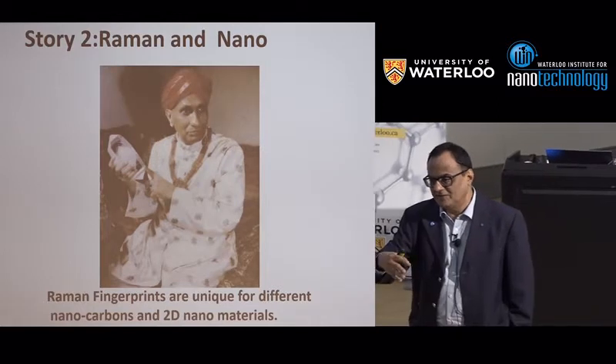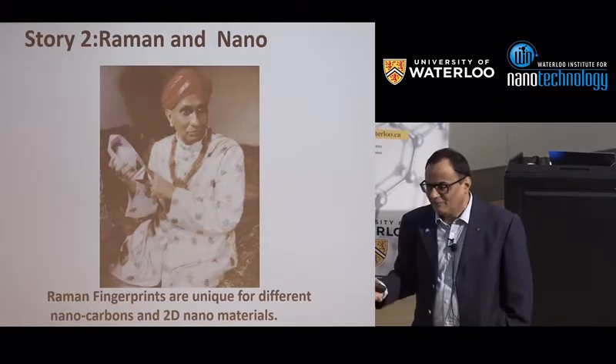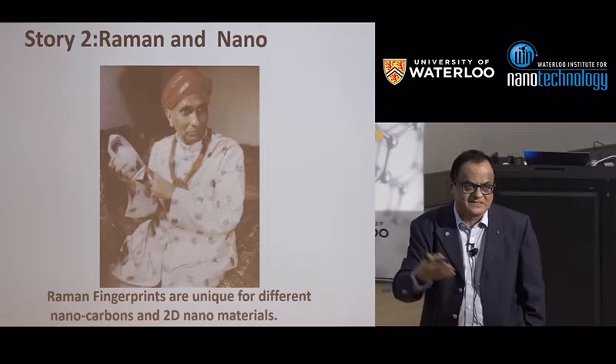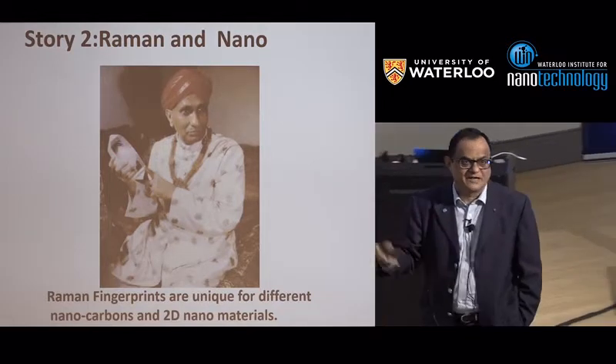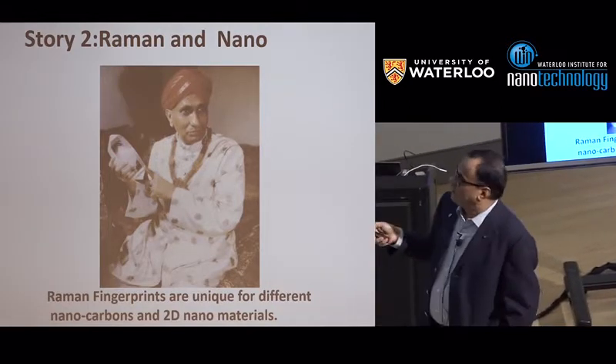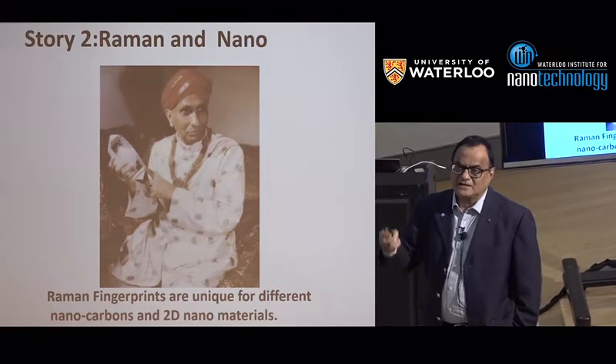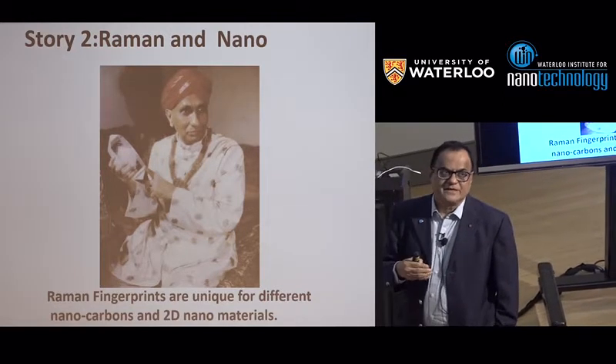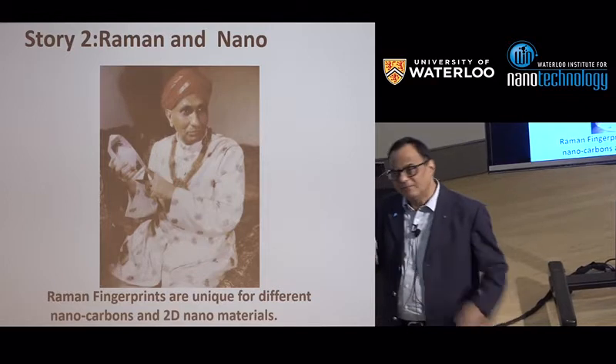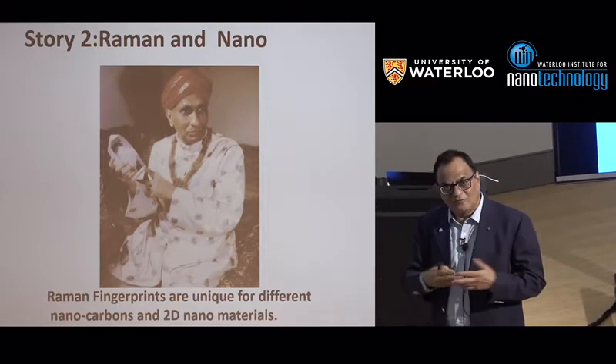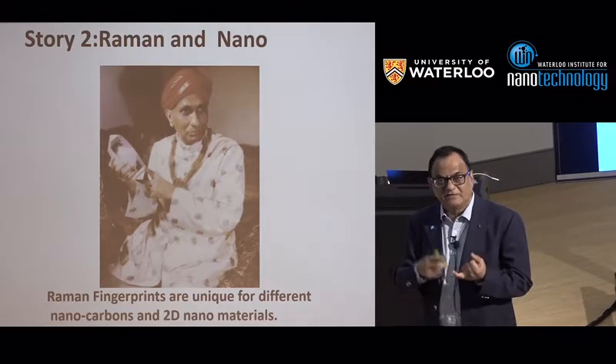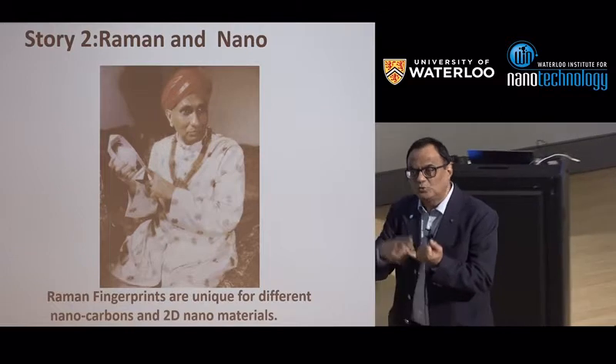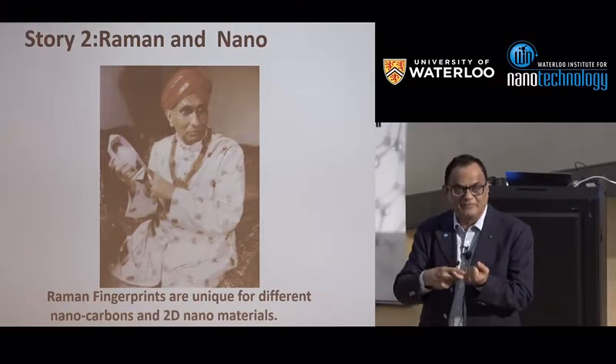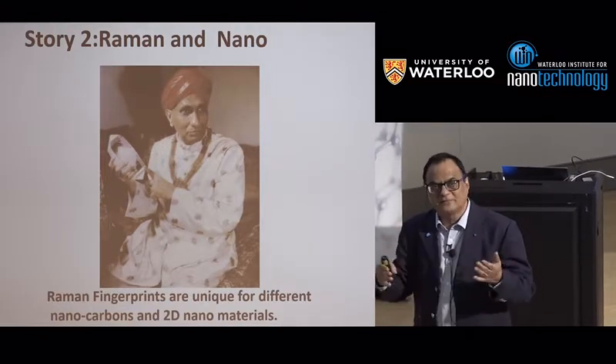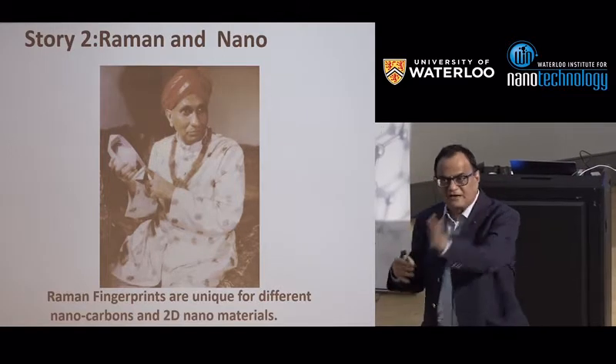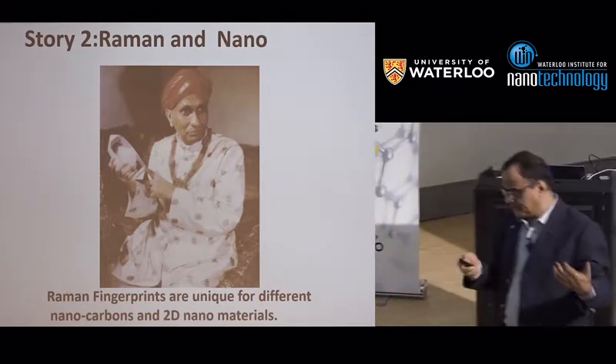I am sure in WIN you will have about 10 of them, because every sample you can characterize very, very fast with Raman spectroscopy. Now, it so happens that in the nano field, Raman has made a big dent because the Raman signatures are very unique of all these nanomaterials, be it one layer, be it 2 layer, be it graphite, be it carbon nanotube. All these materials fortunately have different Raman fingerprints, and you can study them.